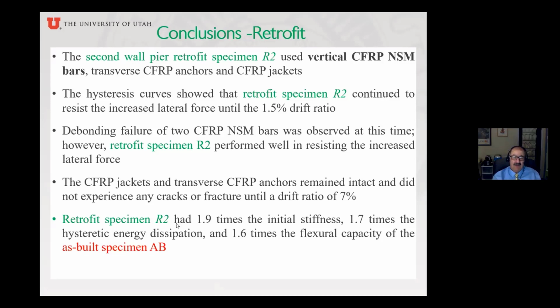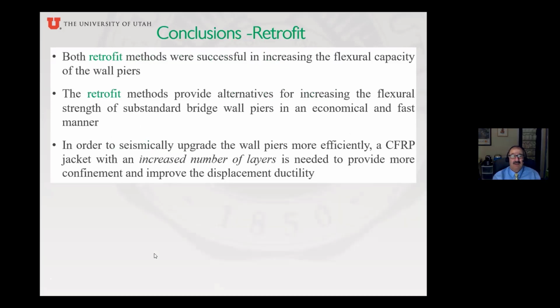So R2 had about 2 times the initial stiffness, 1.7 times the energy, and 1.6 times the flexural capacity. So I would say these two retrofits were very equivalent, and probably these near surface mounted bars, if we were to install them properly, would have done very well. But I would say they were successful. They give you some alternatives for increasing the flexural strength in an economical and very fast manner. I mean, remember, I'm working with 2 students in the lab and we're doing all this ourselves. So I think to make it more efficient, probably the jacket has to have an increased number of layers to provide more confinement and improve the ductility a little bit more.